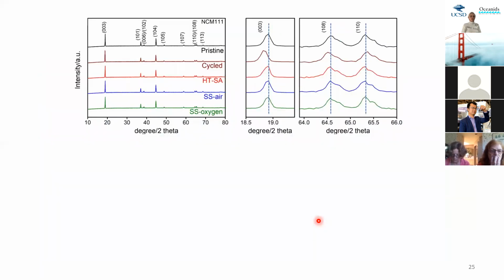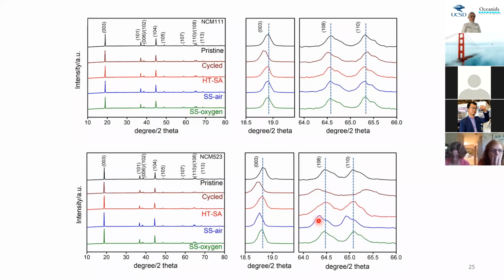So in terms of this microstructure using X-ray diffraction, I don't want to talk too much, but just gives you a very general idea is that if you compare all these patterns, they look similar, right? This is because they are indeed similar. As I said at the beginning, after 300 cycling or one year of usage of cell phone, there's very little change. Okay, all the change happens on the composition on the surface and the phase on the surface. That we can use a small amount of effort to basically shift them back.